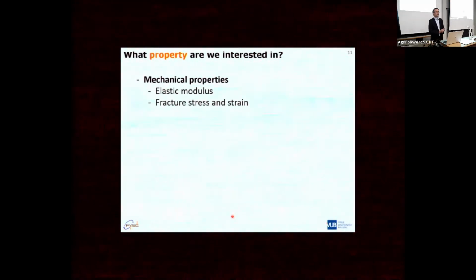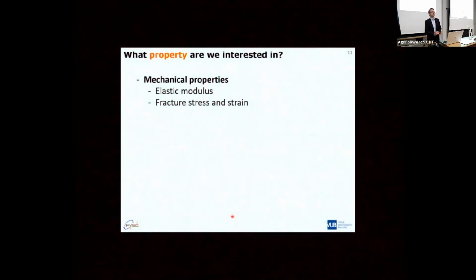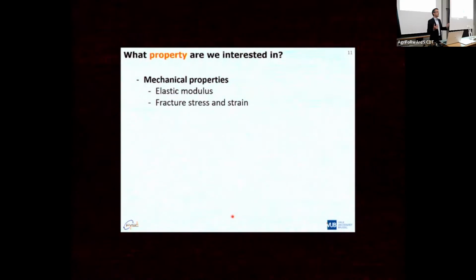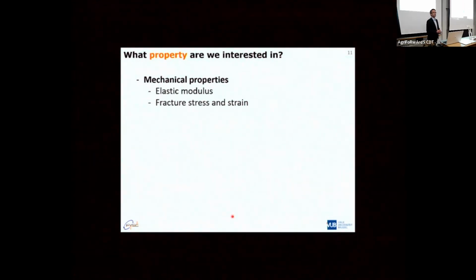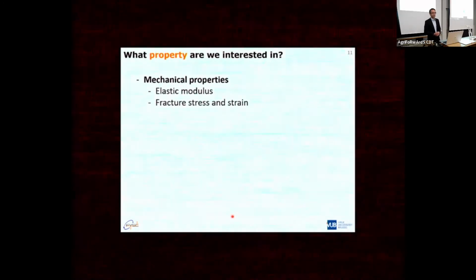Probably quite a few of you have a mechanical engineering background. And if you think about the robot, probably the first thing you think is, okay, I want to get the same stiffness, I want to get the same modulus. Might be the case, but of course, that's not the only thing. You might measure the Young's modulus in the first few percent of strain that you apply to the material, while in your application, it might go to larger strains. And so then, of course, the fracture properties, fracture stress, fracture strain, actually the tensile test curve in all its details might actually become important.